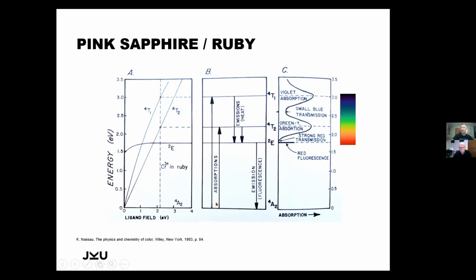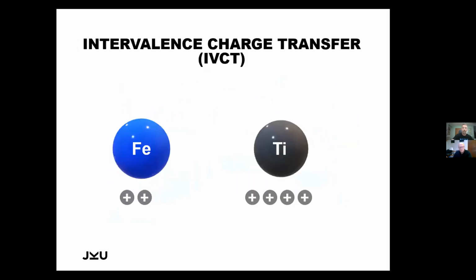So if we heat, if heating is not the right word, if we have any light source that has a higher energy than one of these two levels, the electrons will be pumped up, fall down to the E2 level, and from the E2 level, they give us this nice red fluorescence of chromium in ruby at approximately 692 nanometers, which is the strong red fluorescence that we see when we shine, for example, UV light onto this ruby. So this is the first mechanism that gives us one of the most prominent colors that we have in corundum, the pink to red colors of the chromium inside an aluminum oxide.